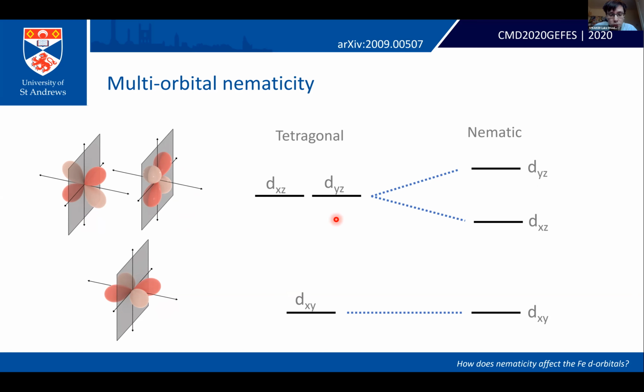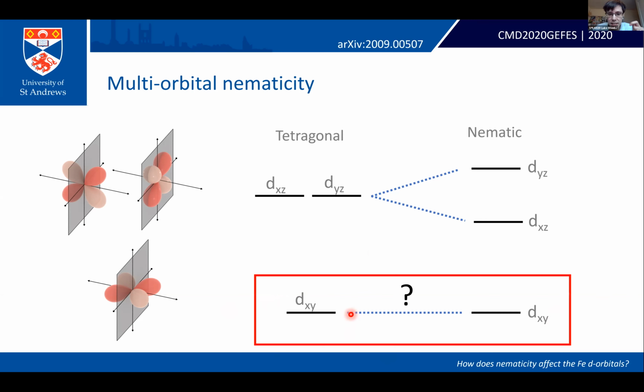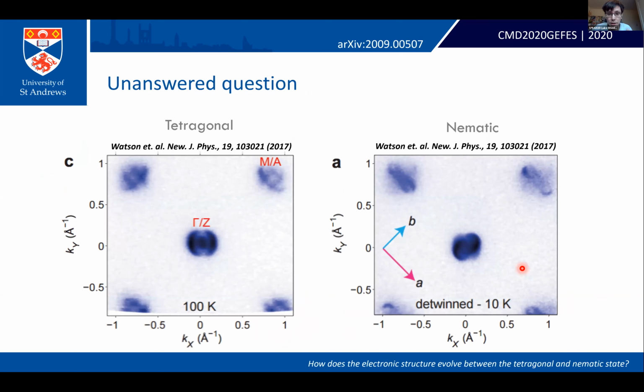Now, for the case of, say, the XZ and YZ orbitals, this is relatively well understood. In the tetragonal state, your XZ and YZ orbitals are degenerate, and that degeneracy is lifted when you break rotational symmetry. But there's a bit more of an open question as to what happens to the DXY orbital upon entering this nematic state. How much this DXY orbital is influenced by nematic ordering. And many theories of the nematic state simply assume that this term is small and negligible. But today I would like to argue the opposite. I would like to argue that this DXY nematic ordering is just as important, if not more important, than the orbital rearrangement of the XZ and YZ orbitals. And the reason I want to argue this is because it will allow us to address one of the central unanswered questions surrounding the electronic structure of iron selenide.